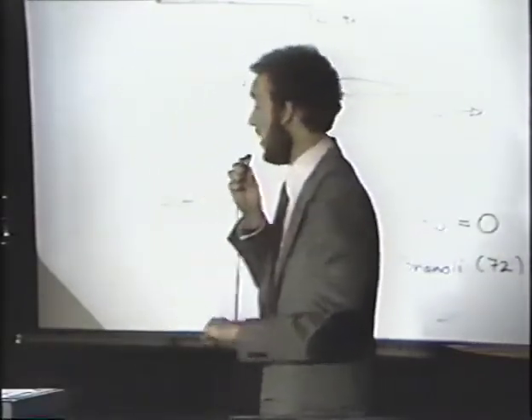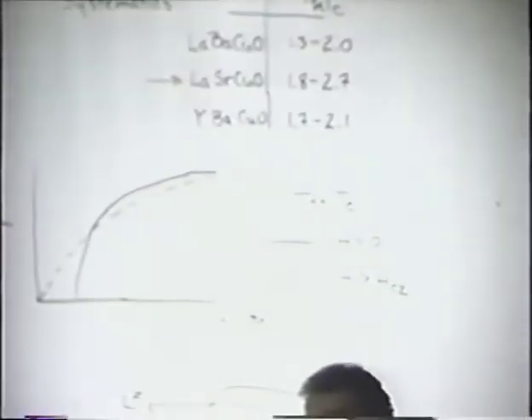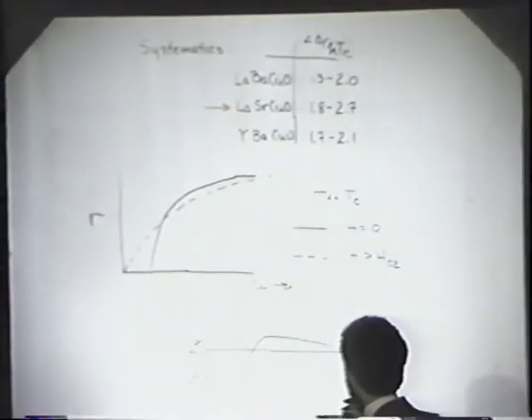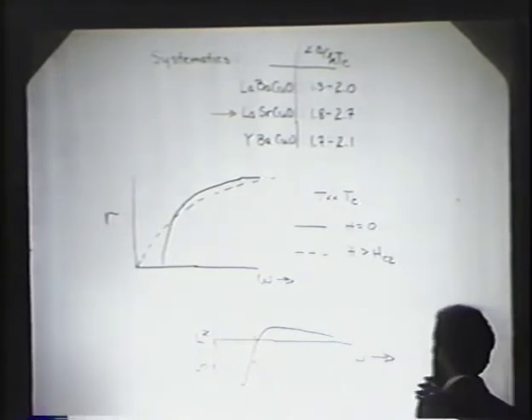First of all, I'd like to thank our many collaborators at Cornell University, Bellcore, Standard Oil, and Temple. As many people have already mentioned, measuring the gap is a very important thing to do. It can be measured either by tunneling or by far infrared spectroscopy. First, we'll just summarize some systematics observed for the three superconducting systems. All three of the systems have a gap, 2 delta over KTC, which is less than the BCS prediction of 3.5. And we'll focus on the lanthanum strontium copper oxide in this talk.